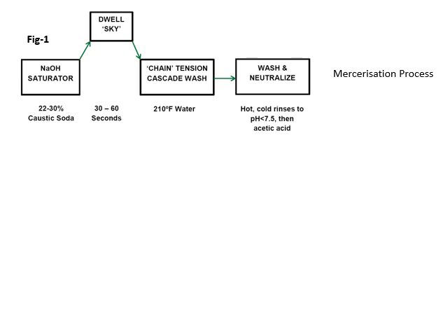The subsequent swelling of the fiber molecules collapses the lumen. The fabric is passed over timing rollers to allow the caustic enough dwell time at ambient temperature to accomplish the process. This step is also called skying.